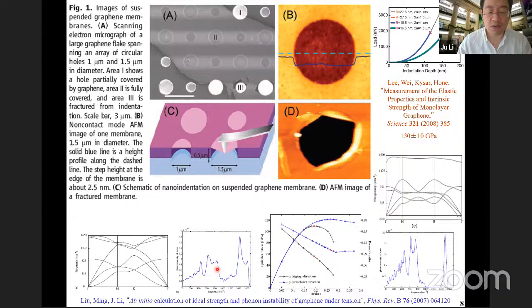But this is a stress strain curve. When you pull it by 20%, with this Poisson contraction, and the stress is 110 gigapascal, we see a very wide phononic band gap open up. Since we know that heat conduction, and in fact electron-phonon coupling and superconductivity, all depend on phonons, the fact that before it breaks it's a very different graphene from our normal graphene is the take-home message. Things like thermal conductivity, electrical properties, and superconductivity are probably all going to change.